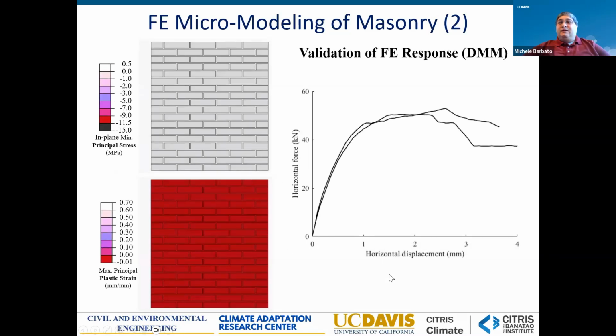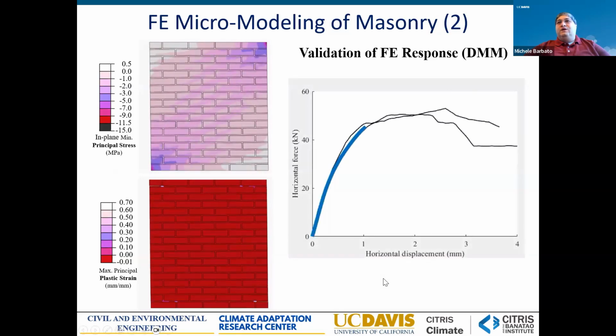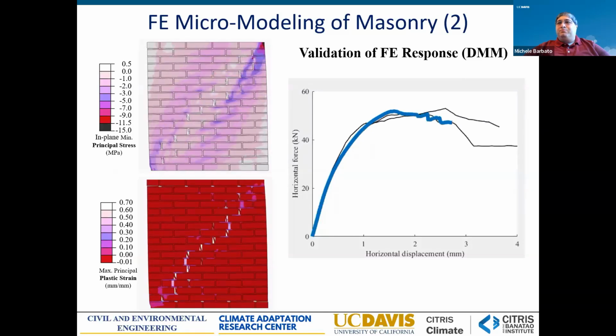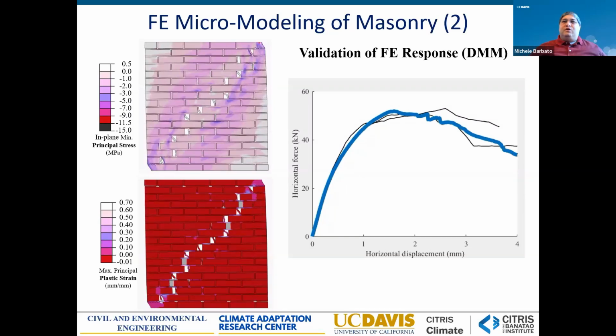So by using the detailed micromodeling approach for an ordinary wall of masonry for which experimental data are available, represented by these black lines, we were able to model the behavior of this structure in a relatively accurate manner. You can see this blue line is our numerical simulations and how it compares with the experimental results. And also on the left side, you can see the development of the principal stress and the principal strain and the plastic strain, as well as the development of the cracking within the structure that again has a very good correspondence with the experimental results.